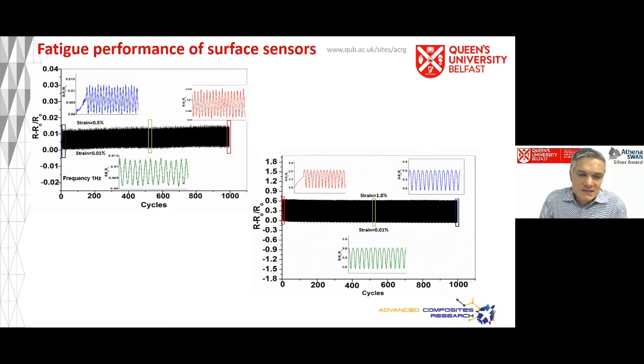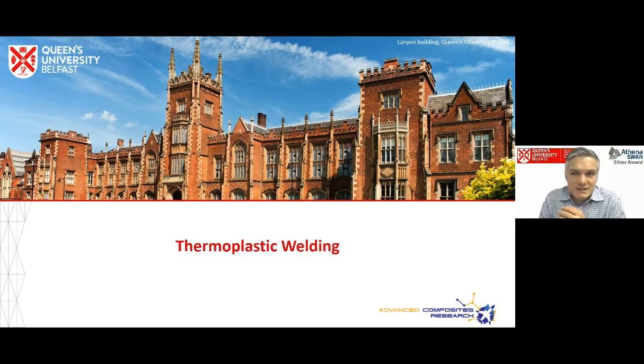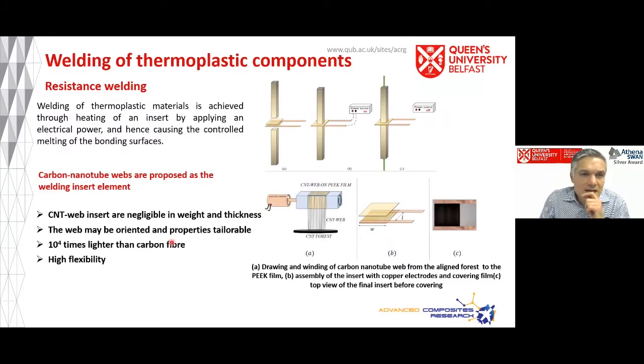And the last thing I want to talk about is something which we're very excited about, and that is as a sacrificial element in thermoplastic welding. And what we've done here is we basically used a similar setup to what we had before, but we've got two copper electrodes, we've got our carbon nanotube web in between, and then we've inserted this between a butt joint, and then through a combination of heat and pressure, we wanted to see how well we could fuse or weld these two thermoplastic components together.